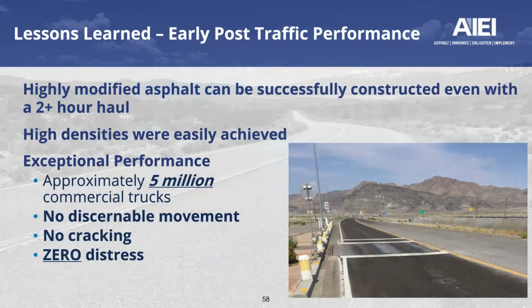What have we seen in terms of performance? We continue to call this early performance, but in June we will hit the 5-year mark. What we found is that successful construction, even with that 2-hour one-way haul, was achieved. The DOT was holding the contractor to their PWL spec only on the top half of those cores. They, as we saw, achieved great density of above 97%, almost to 98%.